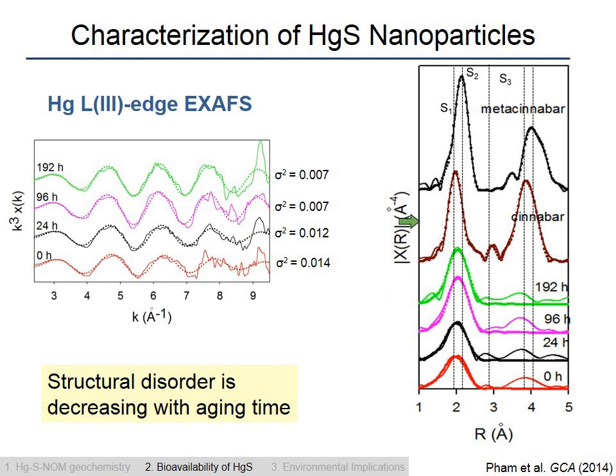So for example, on the top two, I have the radial distribution function that you'd see for two types of mercury sulfide crystals, metacinnabar and cinnabar. And these peaks correspond to atoms that are the closest neighboring atoms surrounding the mercury atoms in the crystal structure. So in this case, the first is the sulfur atom that's neighboring the mercury atom. And then the second one here is the second shell mercury-mercury interaction. The height of these peaks, or you can apply models to these spectra, where as an outcome of the model, you can figure out the coordination number of the structure, as well as the bond distance, and also the crystallinity of the particles that you're measuring.